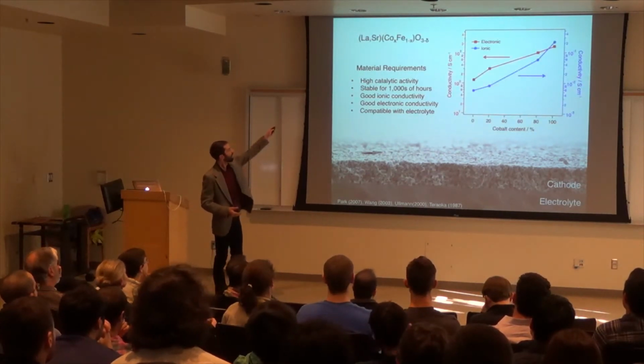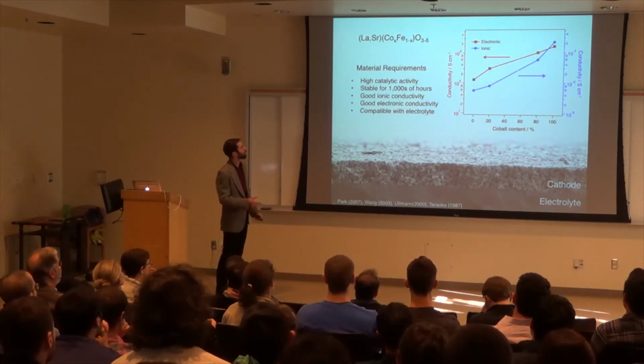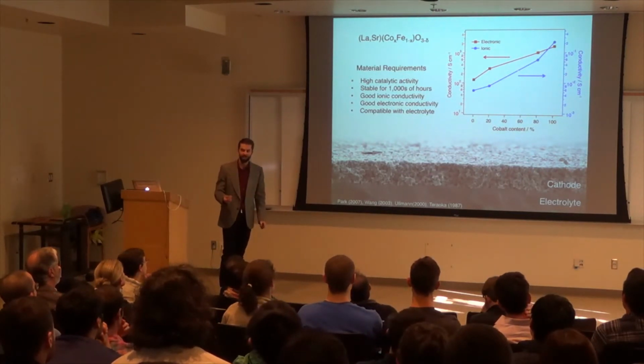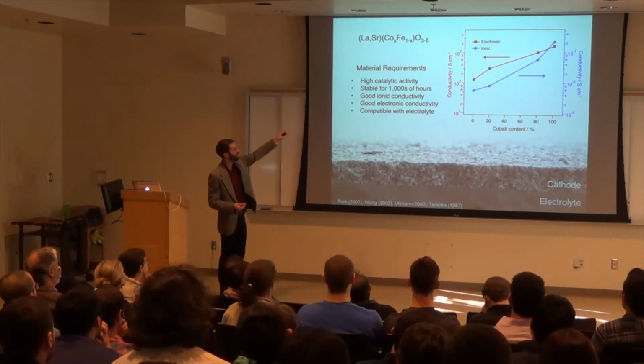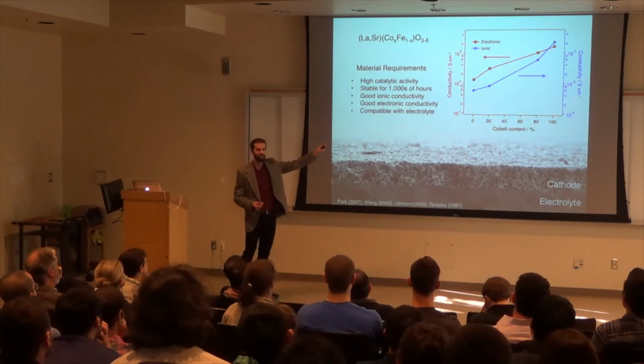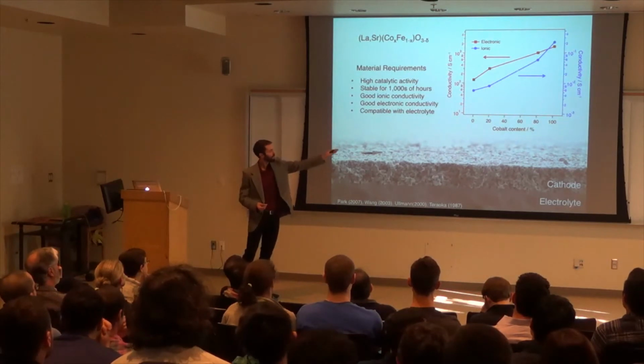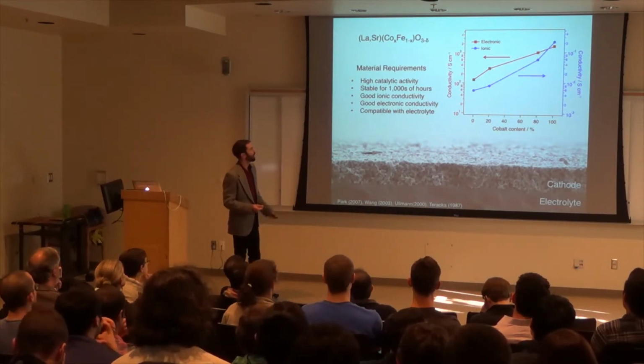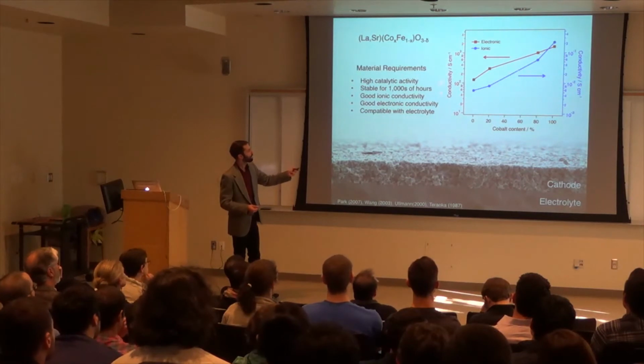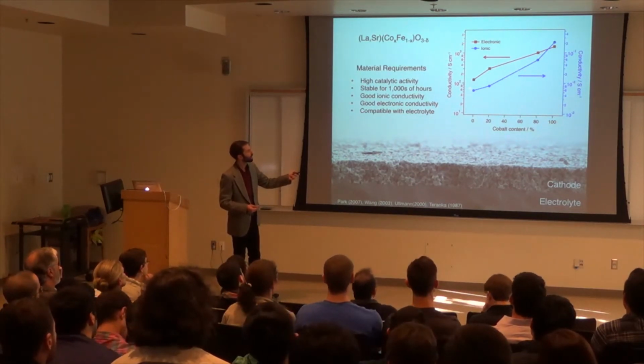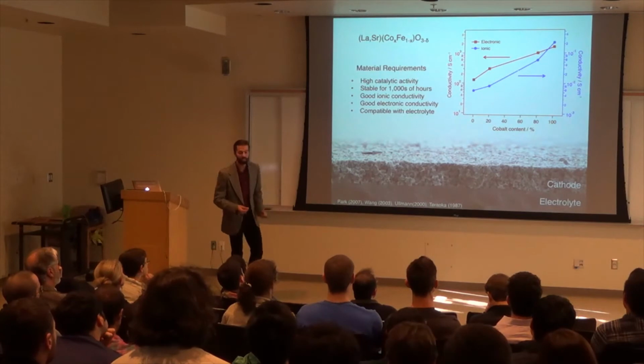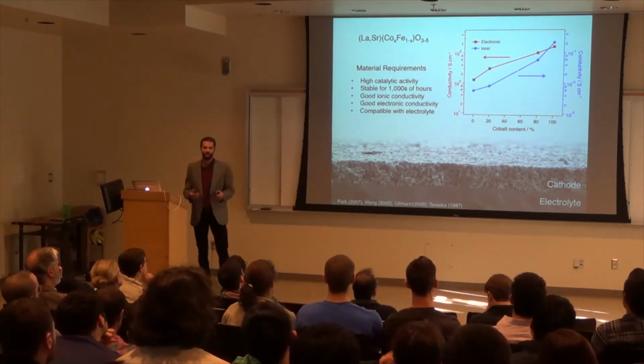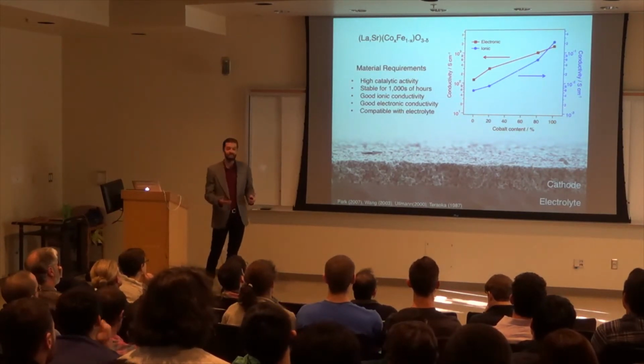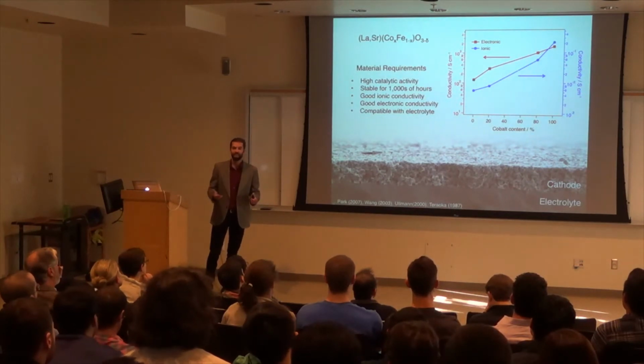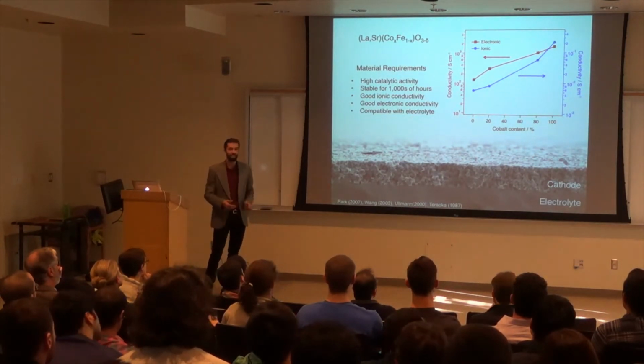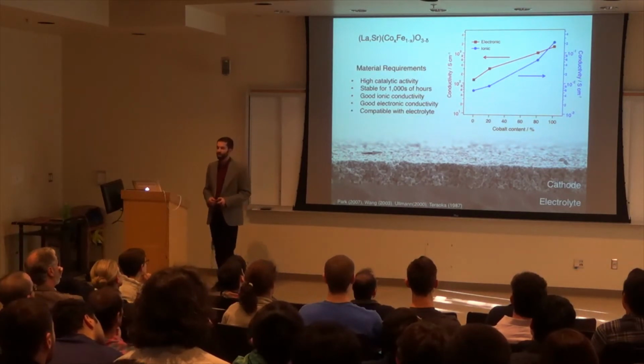So for the material system shown here, we have lanthanum and strontium. Strontium is the alkaline earth element. And then we change the B site from something that has only iron, and we start adding cobalt into it until it's 100% cobalt. And what we see in this graph with conductivity as a function of cobalt content is that both the ionic and electronic conductivity increase. So this basically says that cobalt-containing catalysts are pretty good in a lot of these areas, but they're a little bit unstable, and I'm going to talk to you about why that is.